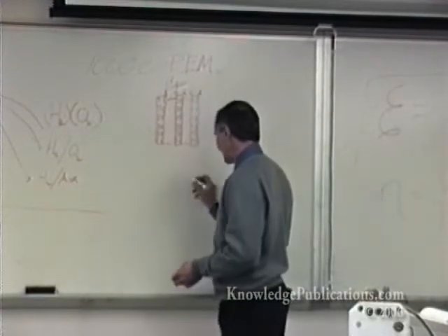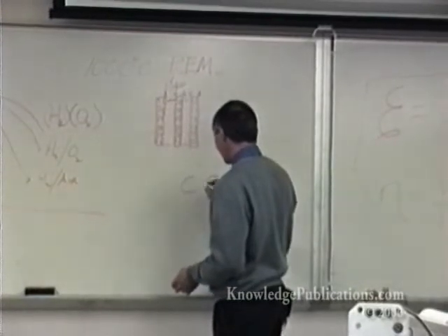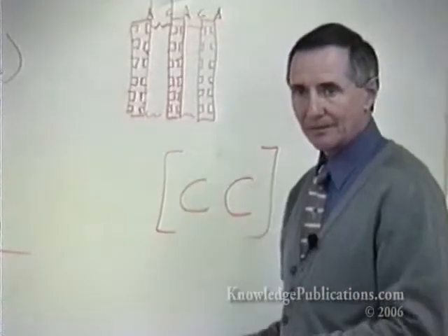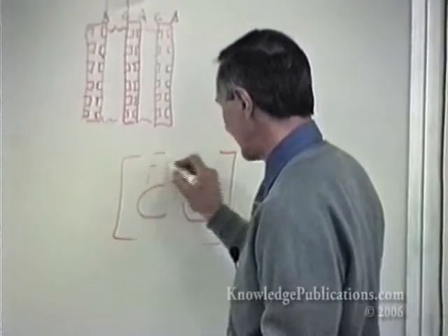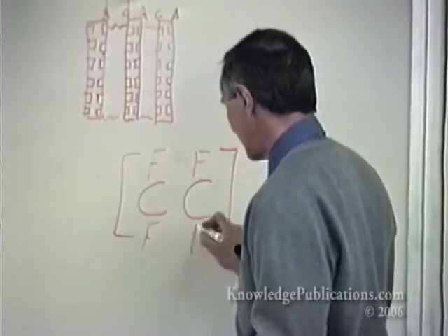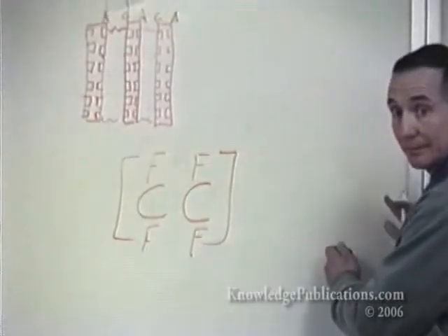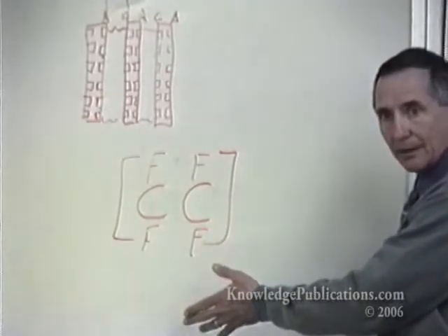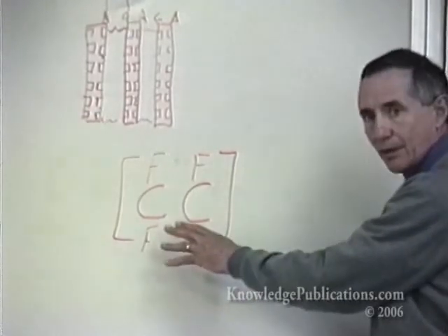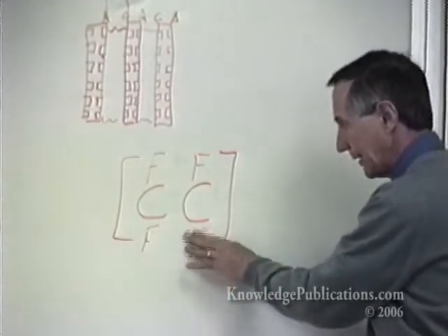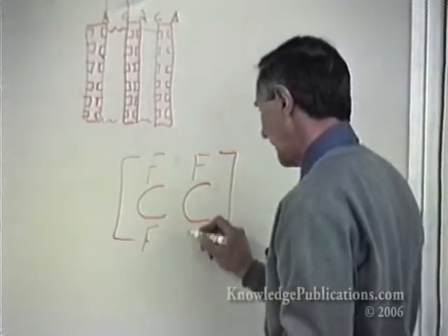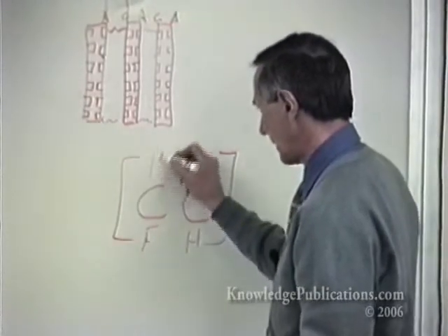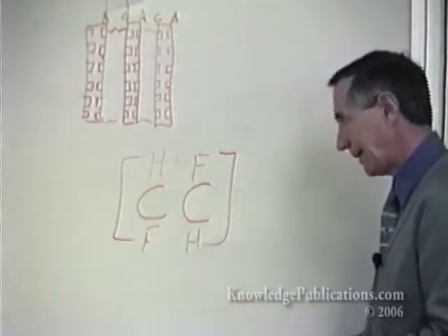Basically, these membranes look like this on a mer basis. If you had traditional Teflon, you'd fully fluorinate it and repeat this cell. But that turns out to be a difficult one to put into solvents. And so you tend to make a perfluoroalkoxy, a more complex form of this, and to not fully fluorinate it. You may have a different structure where it's partially fluorinated like this. It becomes a